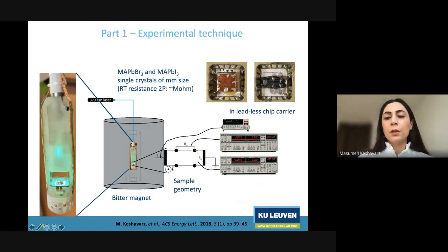In this part, I will only focus on methylammonium lead bromide, whose picture is on the top right, the orange crystals. We did these measurements for methylammonium lead bromide and methylammonium lead iodide single crystals, where we evaporated gold contacts on the crystals and then mounted them on the chip carriers and connected them with silver paste. Then we mounted the chip carriers into our insert, which is coupled to a laser through a fiber. And the laser that we use is a 373 nanometer laser to make sure that we are above the bandgap, exciting above the bandgap.